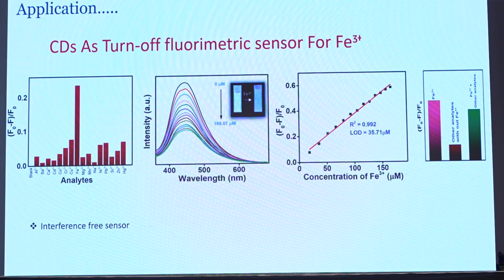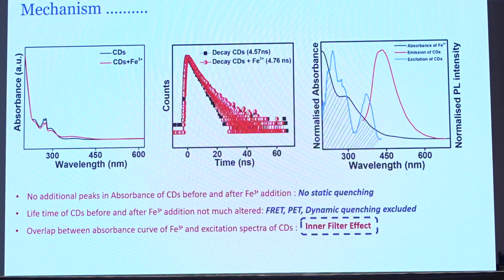and it shows that with ferric ion it shows maximum relative quenching, and we have now checked whether our carbon dot is quenched by other analytes. Without ferric ion, the quenching efficiency is too low, and with the ferric ion together with other analytes, the quenching efficiency is improved. Thus, our carbon dot can be used as an interference-free sensor. Move on to the mechanism.